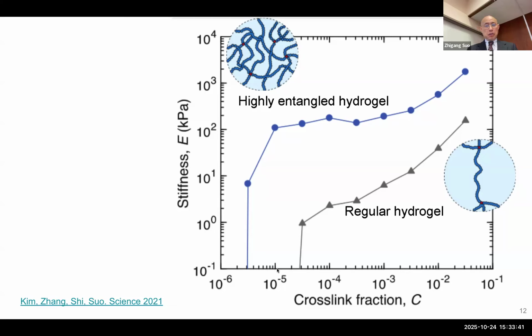After some value, maybe around 10 to the minus 5, which means for every one crosslinker we have 100,000 monomers, so very few crosslinkers, you already reach the modulus. Furthermore, when you increase the crosslinker in this range by about 2 orders of magnitude, you do not increase modulus. That's where we know that your entanglement is about 100 per crosslink, right?